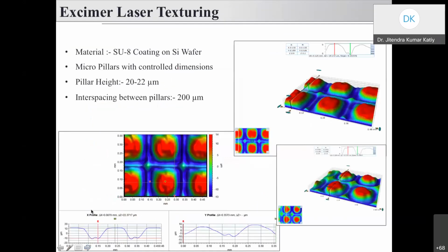Here you can see in the 3D optical profilometer how we can beautifully develop these textures over the silicon wafer, and then we can coat the polymer material to improve their life. The pillar heights which we observed are 20 to 22 micron, and the distance between two pillars is 200 microns. That is easily visible by this